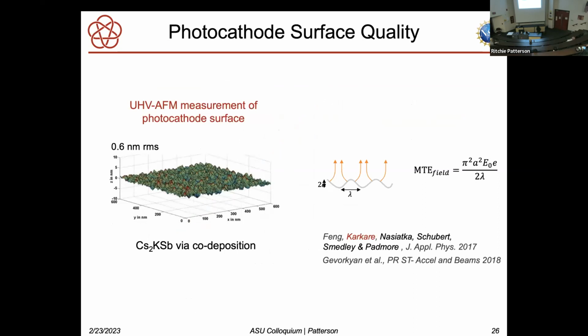One reason for it may be photocathode surface quality. So here's a photocathode surface made through co-deposition, which is a good method, but you see the bumps on the surface, and what happens is that produces an electric field. Remember, this thing is bathed in a very strong electric field that gives a component parallel to the surface, and that creates large MTE, and it especially gets large if you have a strong electric field, which we do.